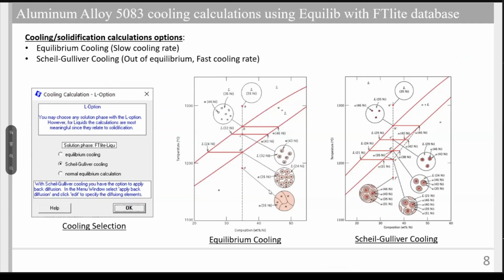So, doing the cooling calculation, you will be given two options: either the equilibrium cooling or the Scheil-Gulliver cooling. Equilibrium cooling, as the name implies, means that the cooling rate is low enough to allow, at every point, the phases to interact with each other. On the other hand, the Scheil-Gulliver cooling happens at a fast cooling rate, which means that the phases once formed will not interact with the liquid anymore and will be permanently locked in.